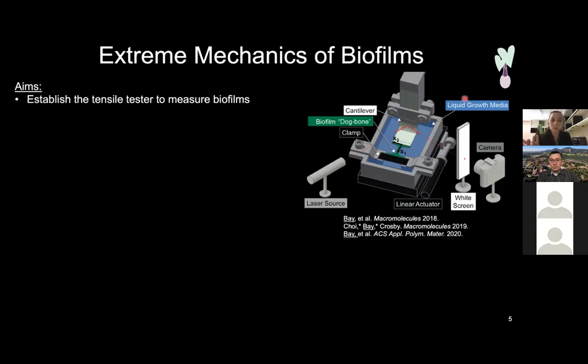Either it can be a liquid growth media, or we can introduce contaminants in the system. And the nice thing about this instrument is that it's mostly off the shelf, where we can buy this linear actuator, this laser source, and the camera, and then everything else, I have the CAD files to 3D print or even machine them, which we've done with these baths before. And so this could be set up pretty fast on an optical table within 3 months.